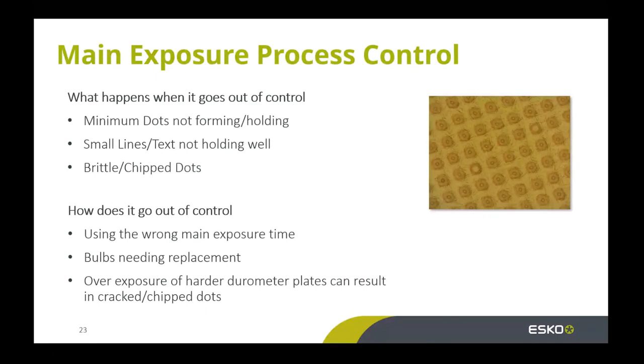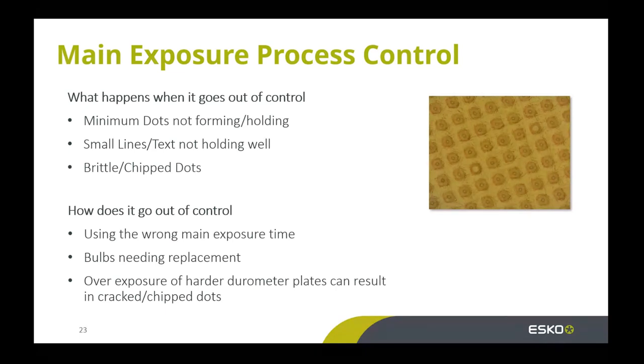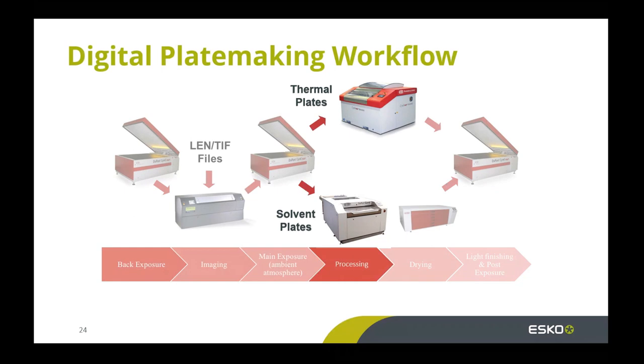How does it go out of control? We've picked the wrong exposure time, or we're looking at the wrong number. From an automated standpoint it's very important to make sure the correct plates are in there and operators are paying close attention. If the bulbs need replacement, that $400 meter makes you very aware of how quickly those bulbs degrade. Ten years ago we used to say 800 hours, today we say 500 to 600 hours - partly because we're putting much finer dots on plates, printing at 175, and 200 lpi on flexible packaging and labels is much more common than just five years ago. With overexposure, you've got a plate that can be brittle, chips on the first rotation on coarse stock, and has to be replaced. The cost of that light meter is more than covered in one hour of downtime on most presses.